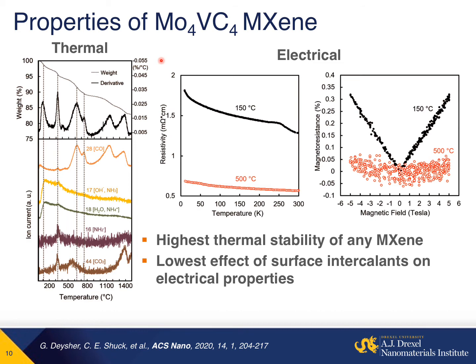So its internal electronic state is not changing as significantly due to changes on its surface. Moreover, what we see is a positive magnetoresistance occurring with this MXene. We're not exactly sure why this has a positive magnetoresistance, but this has been observed a few times with molybdenum-containing MXenes already, and it's something we're investigating further.